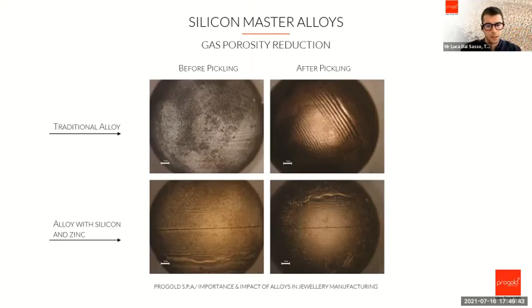Damiano, if you want to add something on this. For gas porosity, you mean, or for this one? For this, just finally, that the barrier, this layer of that compound between silicon and zinc and oxygen, of course, is somehow protecting. The temperature that the investment is reaching when the metal is in contact at its liquid state with the investment is very close to the decomposition temperature of the investment. The decomposition of the investment means gas production, and this gas is somehow not able to enter the piece thanks to this layer that has a very high viscosity.